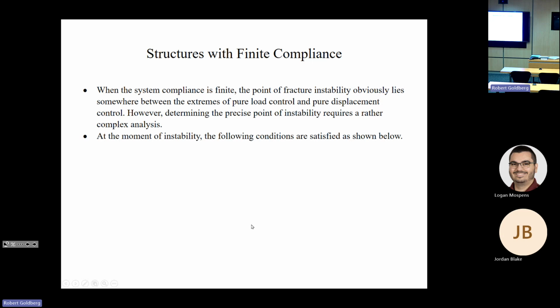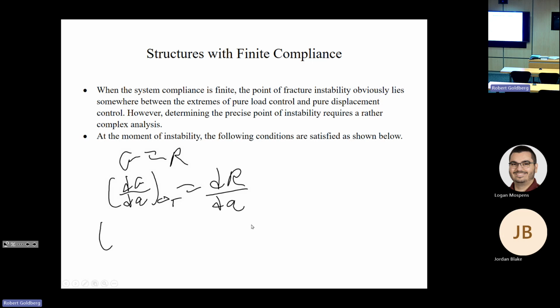However, determining the precise point of instability requires a rather complex analysis. If you have the book, in the appendix of chapter 2 they go through this derivation in detail, but for now we'll just give the results. Instability occurs at the point where the strain energy release rate is equal to the resistance, and the rate of change of the strain energy release rate with respect to the crack size is equal to the rate of change of the resistance with respect to the crack size.